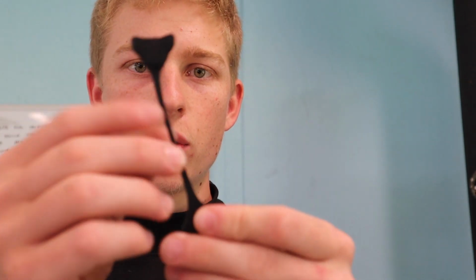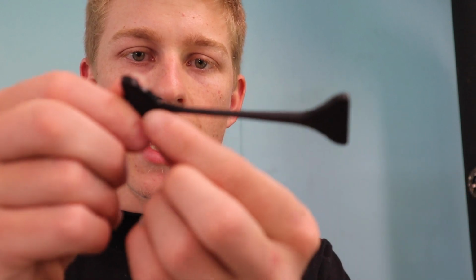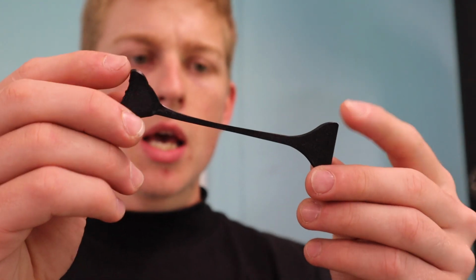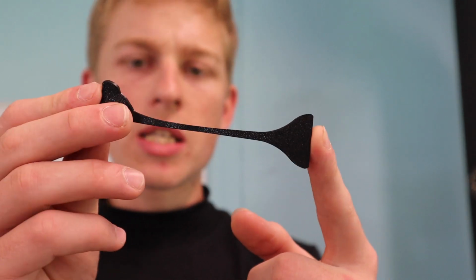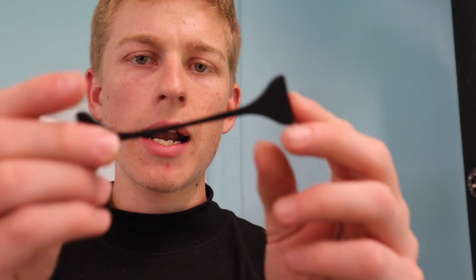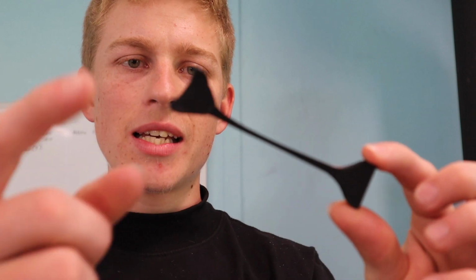That's it, 24 pounds. There's our test sample after the test, and as you can see, that end is pretty deformed. It took almost no force to do this. It just stretched it out. It was pretty soft. It began to kind of yield right here at the neck part. So what kind of happened here was I had the hot air gun blowing on it. You can see this end isn't deformed at all. This end is really deformed.